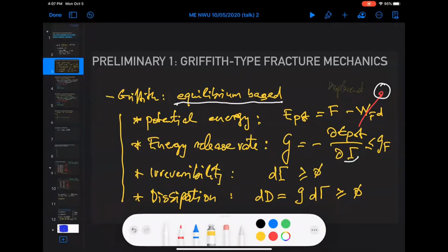We're dealing with an irreversible process, which means that the fracture surface can only increase. And finally, the dissipation here is the product of the driving force, the energy release rate, G, multiplied by the crack surface created. So there's nothing new here, and we'll stick within that framework.